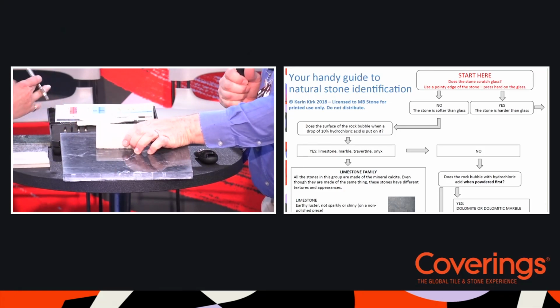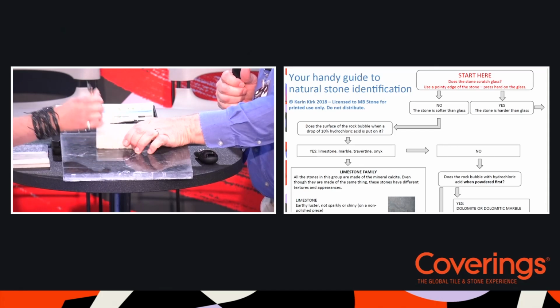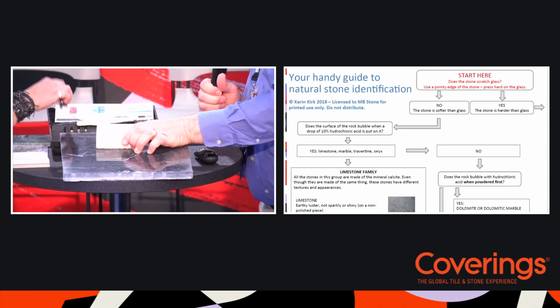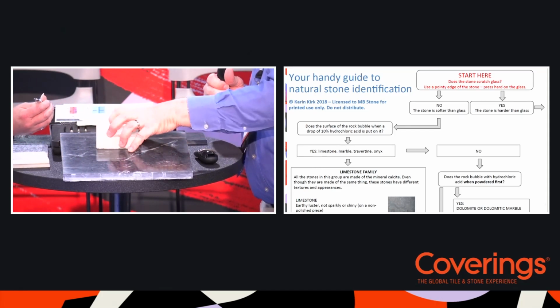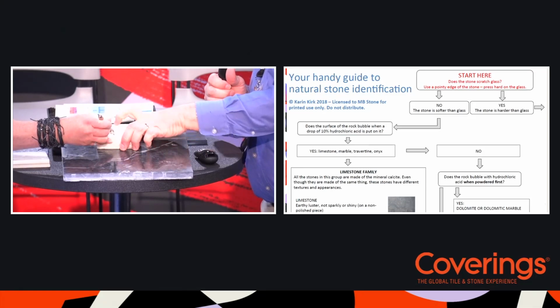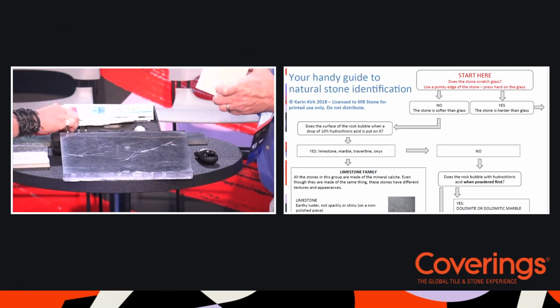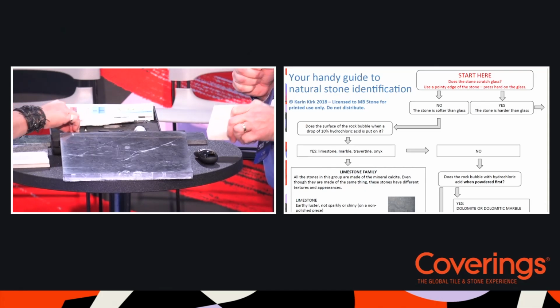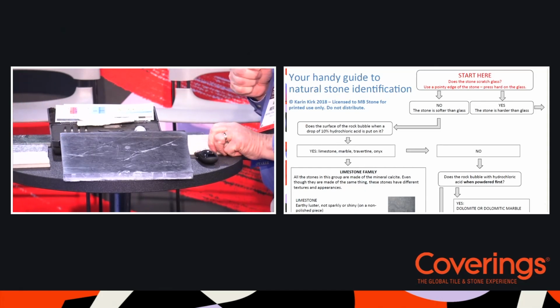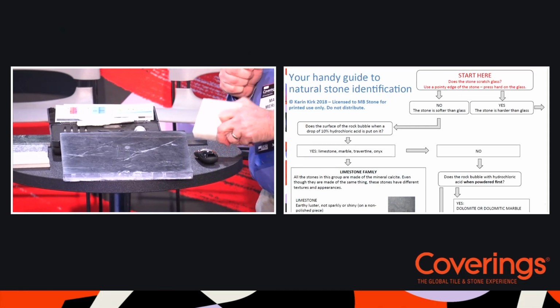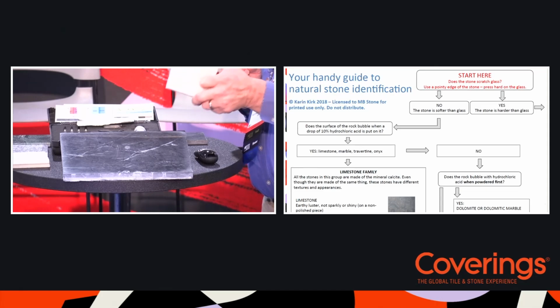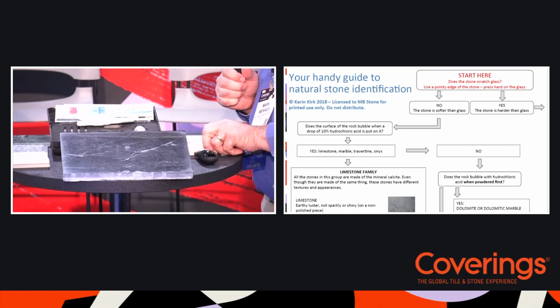That one may be above a 7. Yep. No 7. Nothing yet. That got it. 8 did. So it's up there. This is going to be in that quartzite family. Quartzite will be extremely scratch resistant. It's way up there above the granites. And it should not etch, because it's primarily quartz or silica-based material, not calcium carbonate.